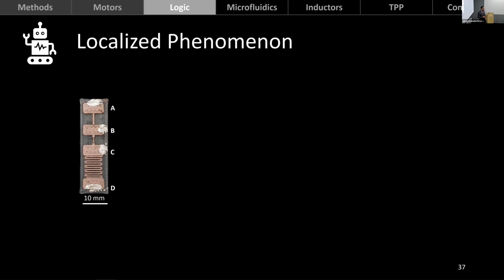And another feature that is interesting about this phenomenon is that it is localized. To illustrate that, we have this sample here with 3 different segments. And we saw that the phenomenon only occurs in the segment that concentrates the highest current density, so the one with the smallest section. With that, we can anticipate that the phenomenon is going to happen here in the BC segment.